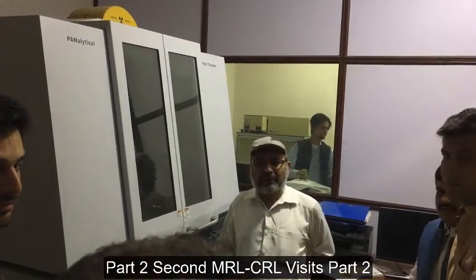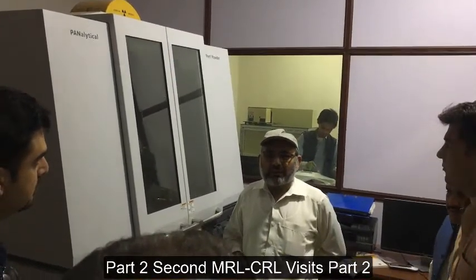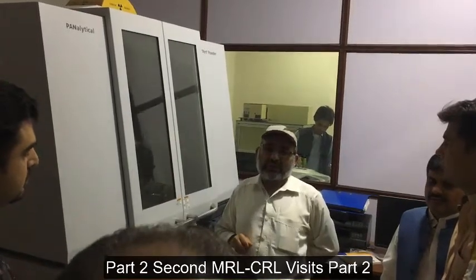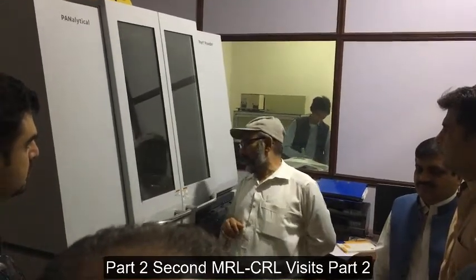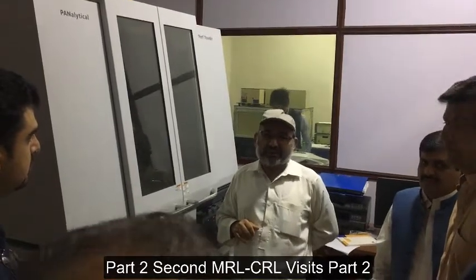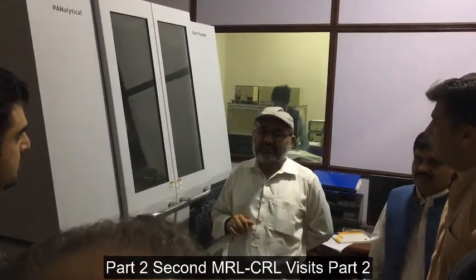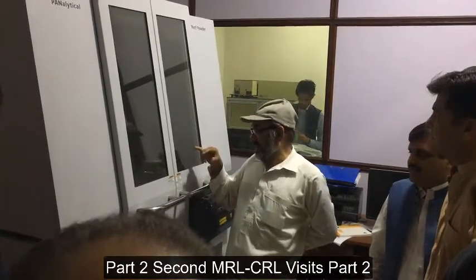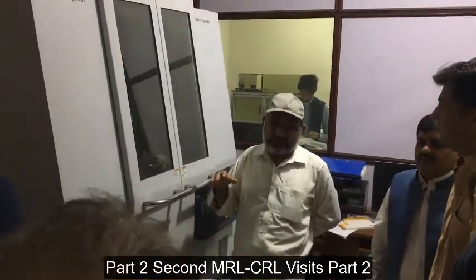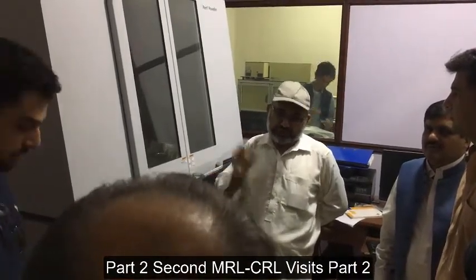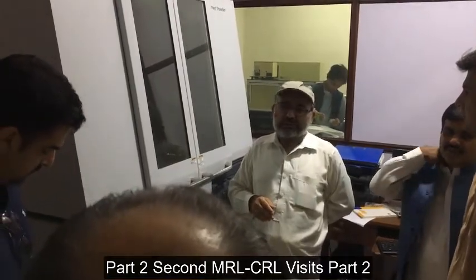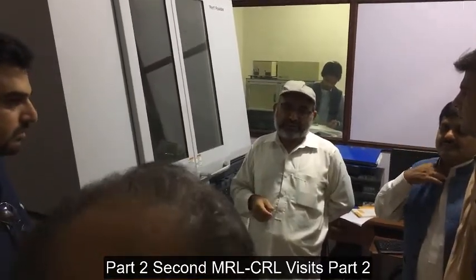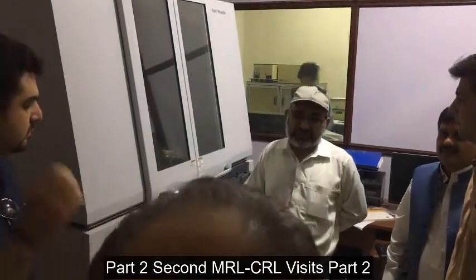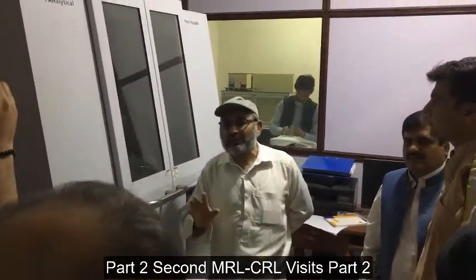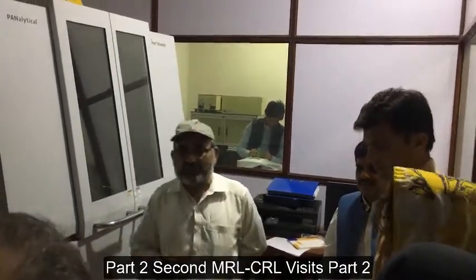We can do only one sample at a time. We have a magazine here, which could do up to probably 35 samples or so. It is not affecting the result, but there is some deficiency which we can't do at a time. I usually did 15, 16 samples in one go, running overnight, but now people don't prefer that. A single sample gives you much safer results, right? And we don't have that facility, otherwise technically there is no problem.